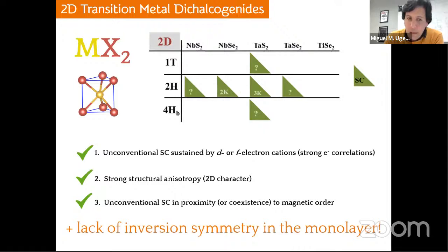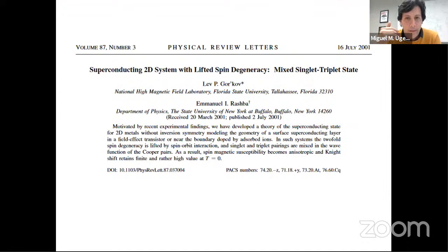But if you look carefully at the properties of these materials, it seems clear that they are in a good position to fulfill the common characteristics of bulk unconventional superconductors. I will go through all of this in a second. And there is one more important thing about these 2D superconductors, which is that in the single layer limit, they lack inversion symmetry. I'm not going to get into details about this, but it's known that in a two-dimensional superconductor where there is a lifted spin degeneracy, for example, due to spin-orbit coupling, which is quite significant in these materials in the two-dimensional limit, a mixed singlet-triplet state should develop. So that's something to take into account as well in order to study these materials.